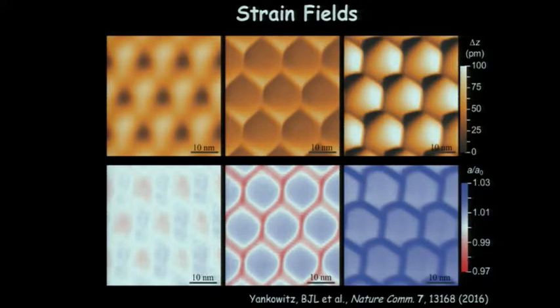Here, this is an imaging condition where we're pushing really hard. And so you can see kind of crazy things happening here in terms of the topography. This is actually a hysteretic regime. It looks different forward and backwards. So we're actually really affecting the sample here. But you could see we could get very large strains just by. Opposite sign as when you were moderate. Yes, they flip signs, which we've never been able to understand exactly why.